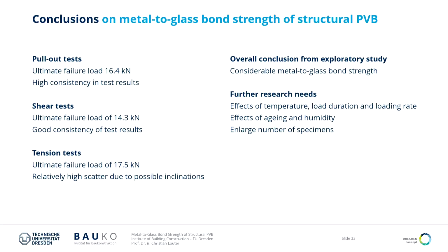So if we then look at the conclusions, the pullout test had a reasonable failure load and a very high consistency. Also, the shear test had a good shear resistance and a good consistency of the test results. For the tension test, we saw some more scatter, but still a significant tension capacity. So overall, we can conclude that the metal-to-glass bond strength of structural PVB is significant and to be considered. And I think you can use it for specific applications within the engineering possibilities. Of course, we need to do further research because this was just an exploratory first study.